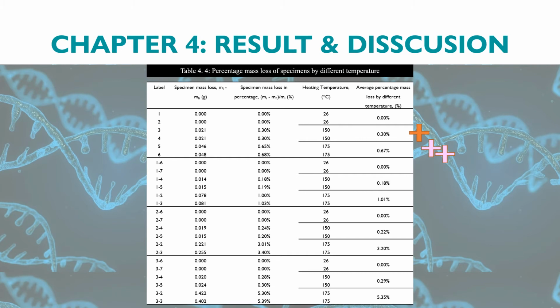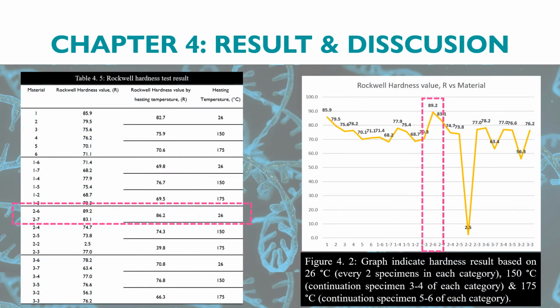However, the TGA result suggested that after prolonged testing and heating, the curve will shift from pure PP to the modified one. On the hardness test, however, it could indicate the real results. There is 1 specimen that has an increased value, which is specimen 27. It is under 80 weight percentage of polypropylene. However, the trend of degradation is affected as the temperature increases. This indicates that heat can affect the mechanical properties. On the other hand, a study of the microstructure to get the best carbon fiber loading might come out with better results.